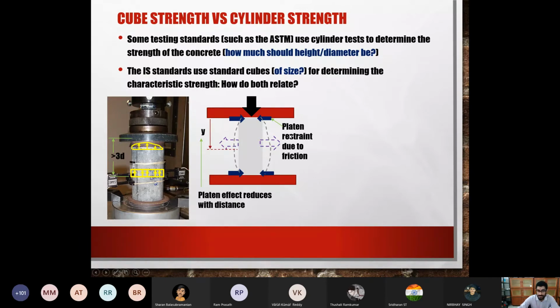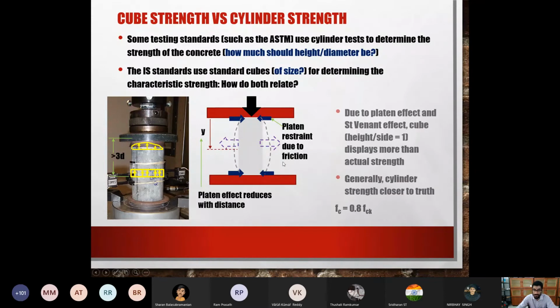So that is one thing. The other thing is, when you press it, the cylinder will try to expand in its middle. However, at the top you have the plate on top and the plate on bottom. At that location, because there's friction between the plate and the surface of the cylinder, it cannot expand that much, because the friction force opposes this expansion. That is known as the platen effect.